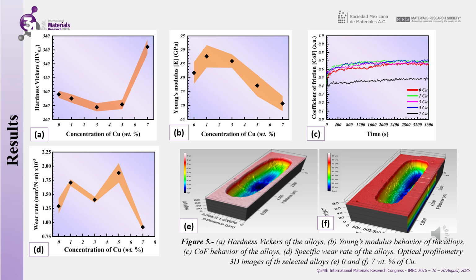the surface. As illustrated in Figure 5d, the specific wear rate, expressed in cubic millimeters per Newton meter, is depicted as a function of the copper concentration. These results demonstrate a distinctly non-monotonic trend. The copper-free alloy demonstrates a wear rate of approximately 1.3 times 10 to the power of negative 3 cubic millimeters per Newton meter. The incorporation of 1% copper results in a substantial increase of the value to approximately 1.7 times 10 to the power of negative 3 cubic millimeters per Newton meter, signifying a decline in wear resistance. Subsequently, at 3% copper, the rate decreases to around 1.4 times 10 to the power of negative 3 cubic millimeters per Newton meter, whilst at 5% copper it increases again, reaching approximately 1.9 times 10 to the power of negative 3 cubic millimeters per Newton meter.